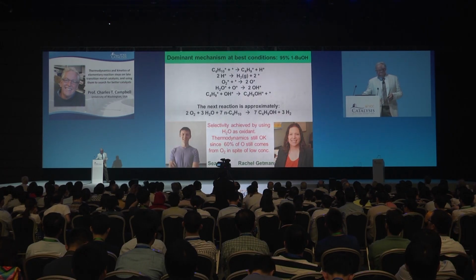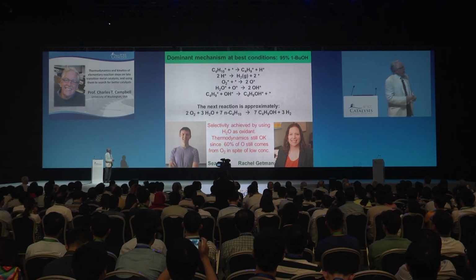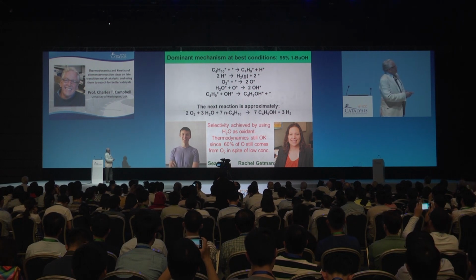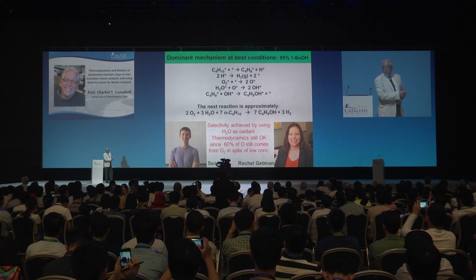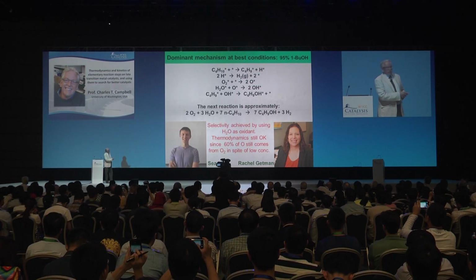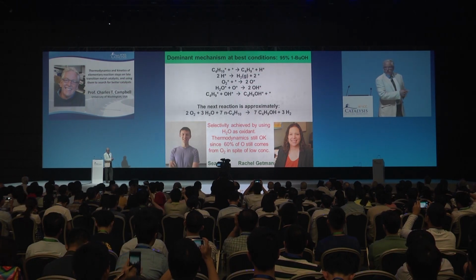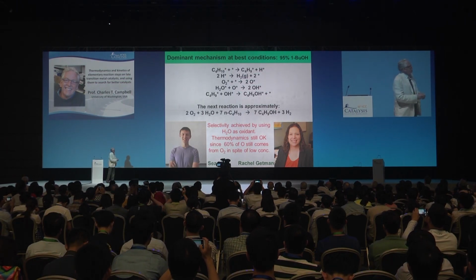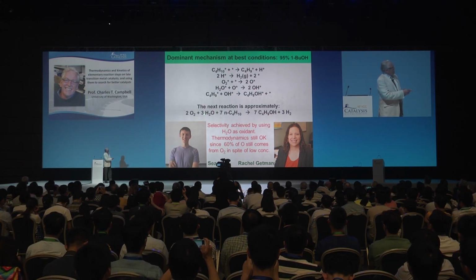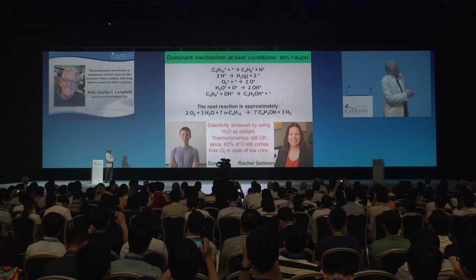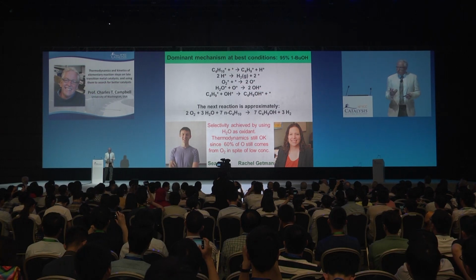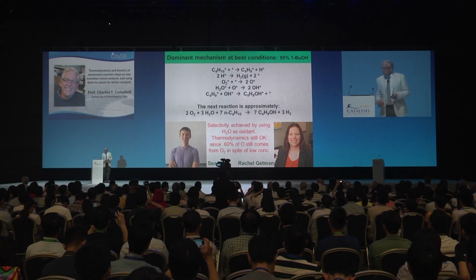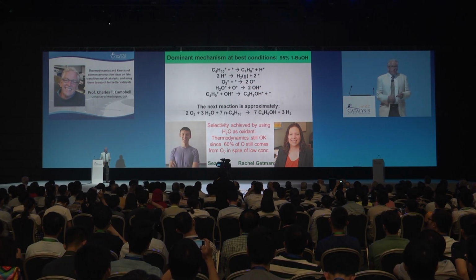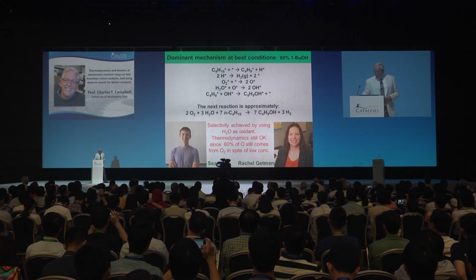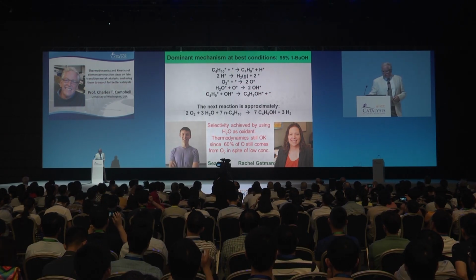It's a little gory about how to do that, but it turned out that once we made those changes, the net reaction wasn't oxygen plus butane going to butanol. We added water to the feed to get more hydroxyls on the surface, and the net reaction was this, where 3 out of 7 of the oxygens in the product were coming from water. And that really led to tremendous selectivity. It gives ideas for how to do selective oxidation, I think, in catalysis.